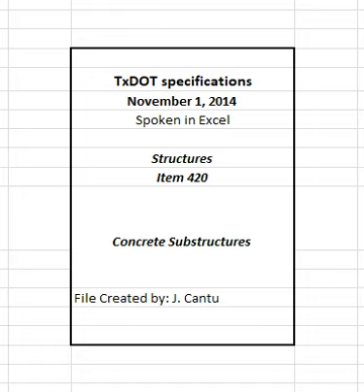4.10.3 Membrane curing. Choose either type 1D or type 2 membrane curing compound unless otherwise shown on the plans. Use the same type of curing compound on an individual member. Apply membrane curing just after free moisture has disappeared at a rate of approximately 180 square feet per gallon. Do not spray curing compound on projecting reinforcing steel or concrete that will later form a construction joint. Do not apply membrane curing to dry surfaces.